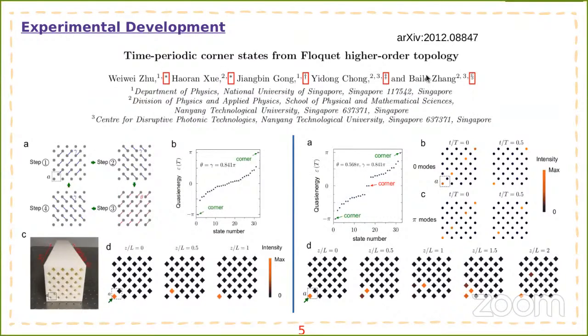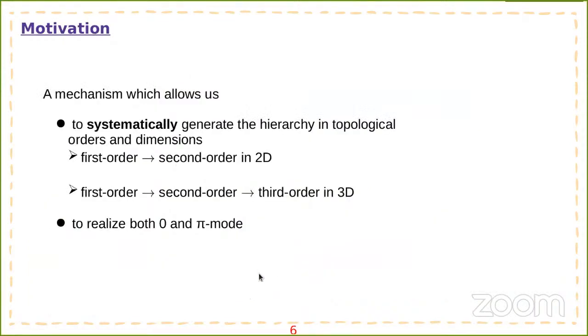So in these experiments, the authors propose a 4-step drive using an acoustic lattice, and using this experiment, they were able to actually show that they can get 0 and pi corner modes, which are localized at the corners of the system. Okay, so with this previous work, what we want to do in this work is systematically generate the hierarchy of topological orders, and also in dimension.